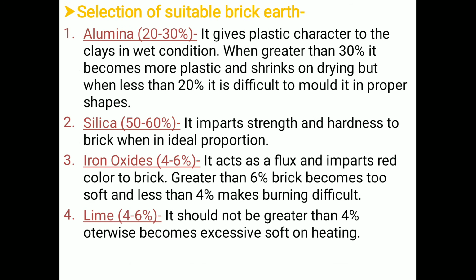Now we will discuss the second point, the selection of suitable brick earth. Brick earth means clay. Whatever clay we select, that clay must contain alumina, silica, iron oxide, lime and magnesia, because all those ingredients have a specific effect on the characteristics of the brick. First of all we will discuss alumina. The percentage of alumina in brick clay is 20 to 30%.